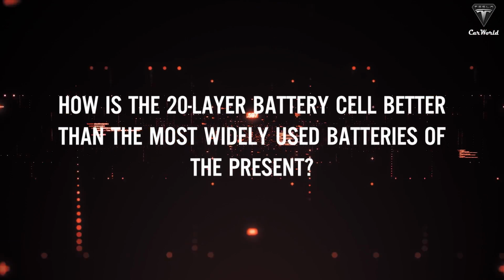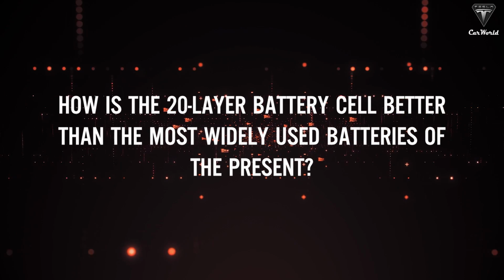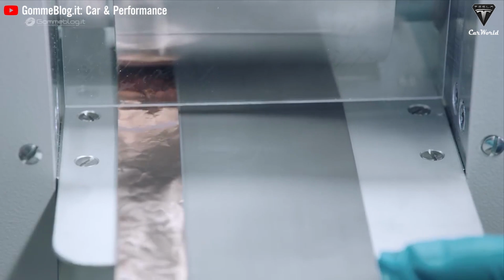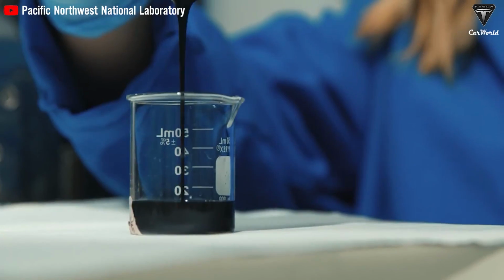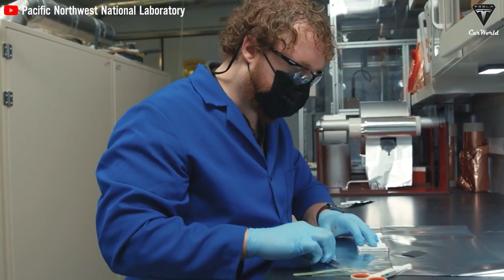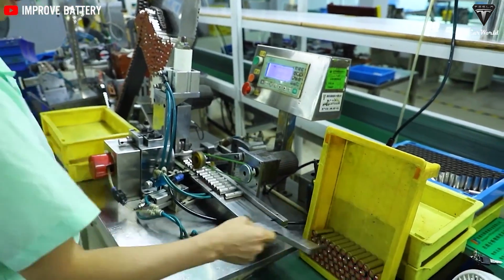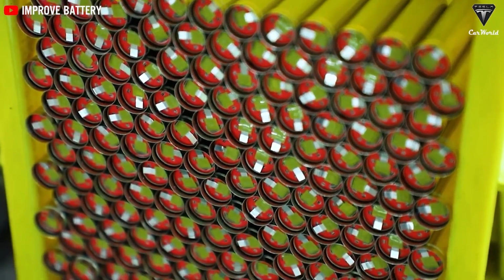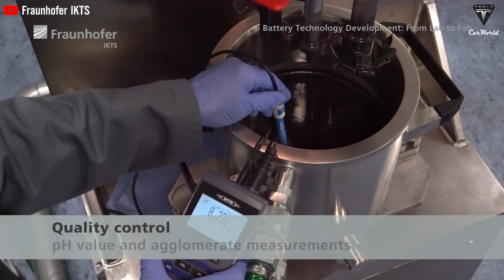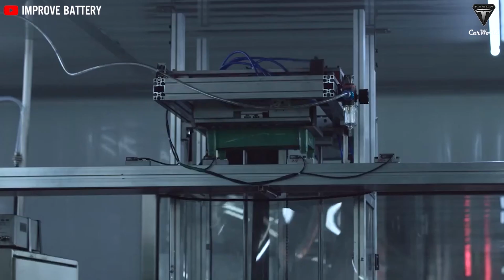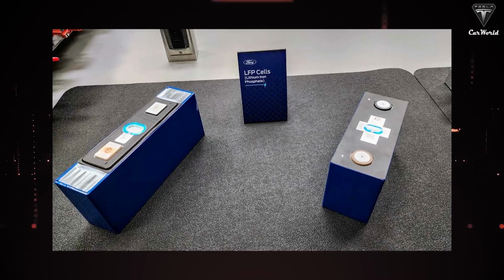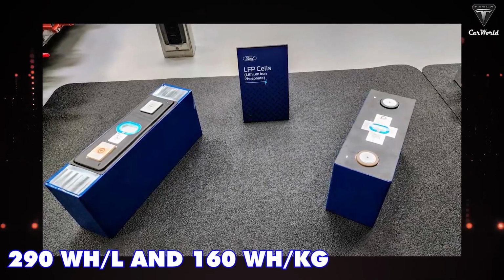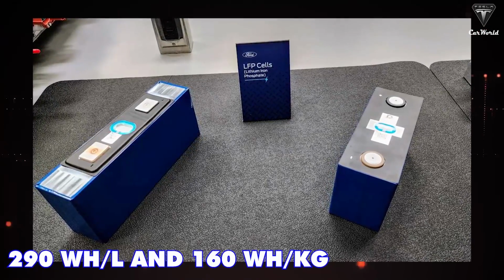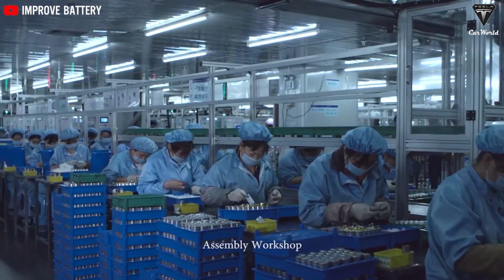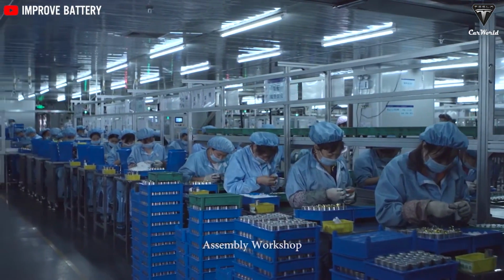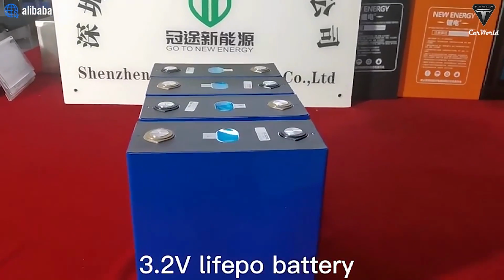How's the 20-layer battery cell better than the most widely used batteries these days? In the realm of battery technology, various enhancements have been made in pursuit of higher energy densities and improved efficiency. Comparing different generations of batteries, we find interesting variations in energy density metrics. For example, the third-generation lithium iron phosphate, or LFP, cell boasts an energy density of 290 watt-hours per liter and 160 watt-hours per kilogram, which is about 1.37 times lower in weight energy density than the 20-layer battery cells.